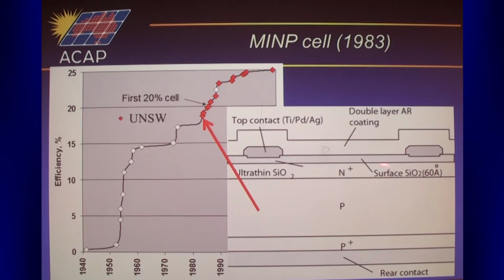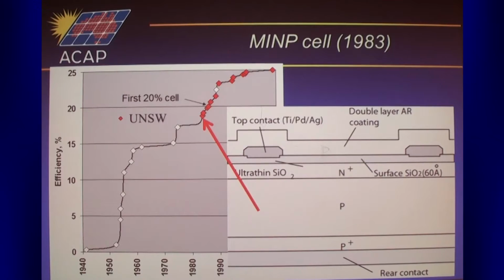But what we did to try and control the surface recombination velocity, we were trying to fix up the emitter of the cell first. So we said we've got to get that S as close to zero as we can. It turns out a native oxide on silicon is a really good way of neutralizing the electronic activity of a silicon surface.